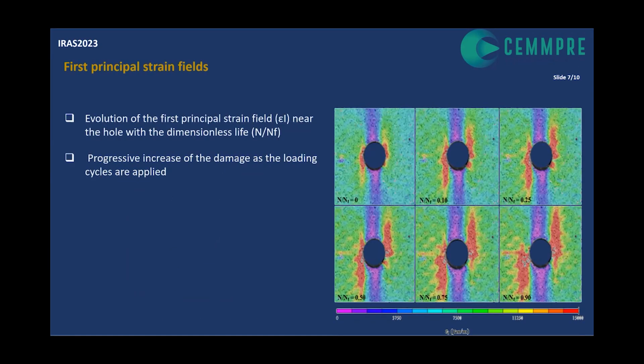In this slide, we have the evolution of the maximum first principal strain around the hole with the number of cycles. This was recorded using digital image correlation. These results clearly show a progressive increase of the damage as the loadings are being applied. It can also be seen that damage patterns are similar for all cases, and we can see an asymmetry in the strain fields, although the loading was uniformly applied on the surface. This asymmetry is caused by two layers of unidirectional laminates, oriented with an angle of 45 degrees relative to the direction of the loading.